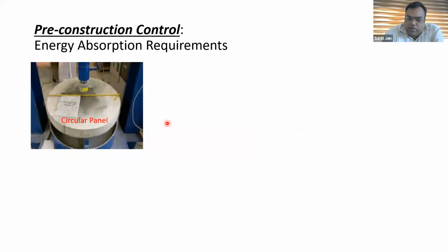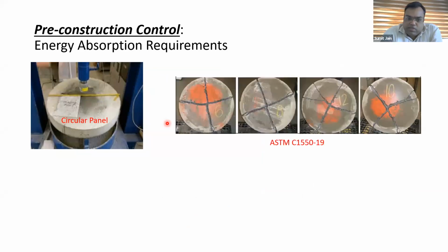This is just a fallback of the previous test. So these can be done on circular panels as well as on the square panels. Circular panels are tested by ASTM standard C1550-19, and we can see there is a plunger which is pushing the panel in the center, and the panel is held at the bottom at 3 points. And this is the typical star crack pattern which we get.